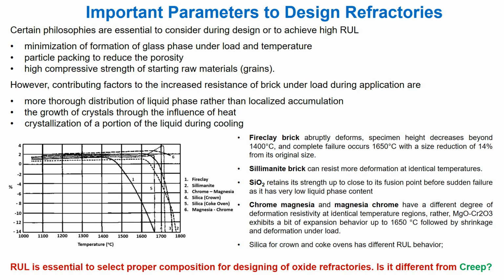Certain philosophies are important to consider during design to achieve high RUL. Minimization of formation of glass phase under load and temperature, particle packing to reduce the porosity, high compressive strength of starting raw material grains, that means without any micro crack of the grains, and high density of the grains.